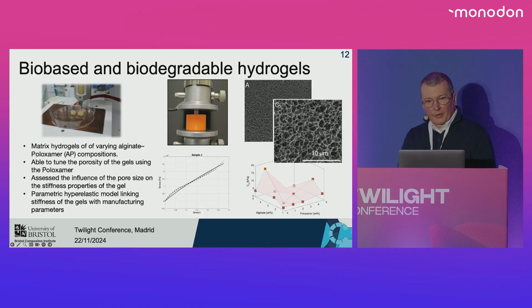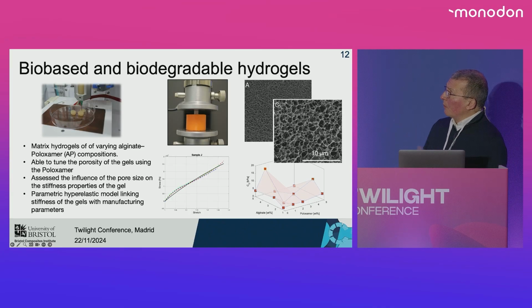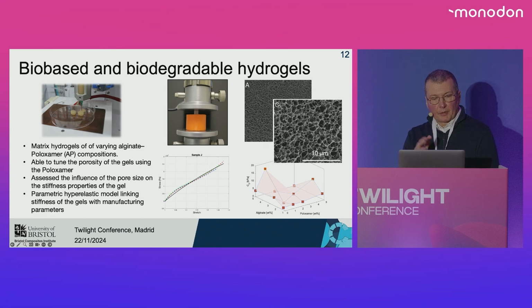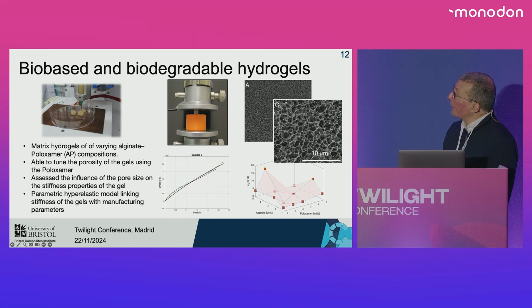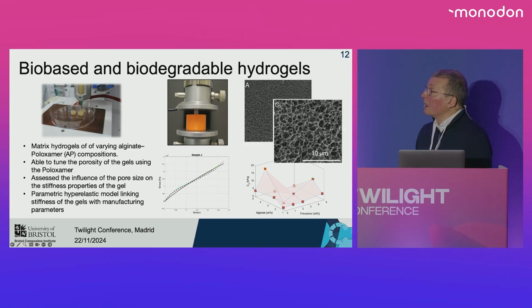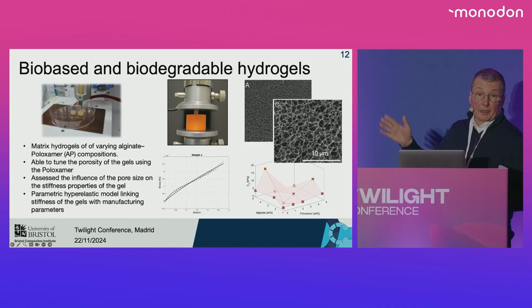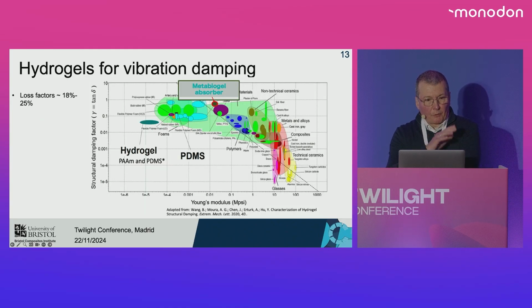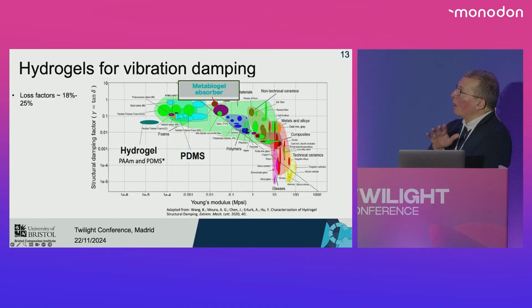So what we have seen so far is very much on the bio-based side, but it's also possible to use softer materials. We have been working on this class of bio-based alginate poloxamer hydrogels with different types of composition, and we have developed techniques to control the pore size at multi-scale level. And typically, the stiffness of these types of composite, the quasi-static stiffness under compression, is between 90 and 130 kilopascal. The interesting fact is when you use this hydrogel base with particular classes of natural fibers, and not necessarily flax, but another class that is under patent,